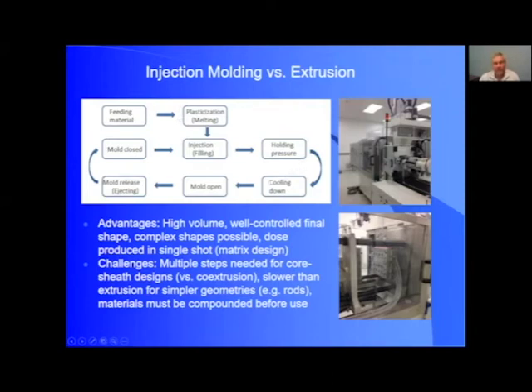So for injection molding, some of the advantages that we believe, you can see here on the right-hand side, one of our larger injection molding machines. This one has about a 300-ton compression. So the more force you can hold the mold closed, the higher the pressures you can inject with. You can typically have more cavities, make more parts with higher total volume and mass. So you can see here inside, this is an injection mold that's approximately, I think, about 18 inches square, water cooled, and